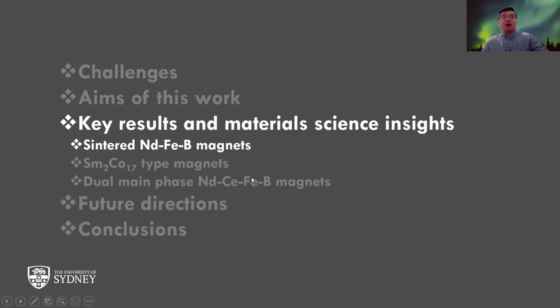Next, I would like to show how I bridge the microstructure, mainly characterized by atom probe tomography, with the magnetic properties simulated by micromagnetic simulations in three types of magnets: the sintered Neodymium Iron Boron magnets, the second generation samarium cobalt based magnets, and also a recent Neodymium Cerium Iron Boron magnet. The cerium is quite cheap, but the intrinsic property is not that good. But we are using a new fabricating technique, called the dual phase technique, to enhance the properties here.